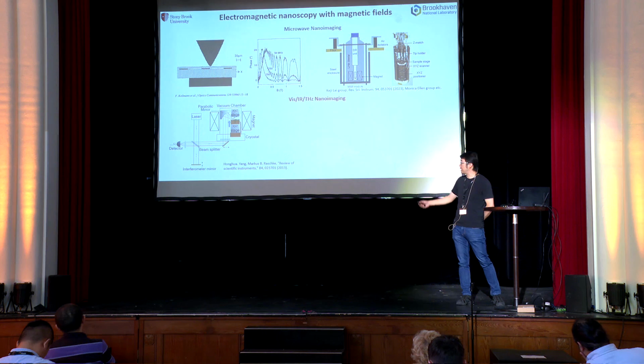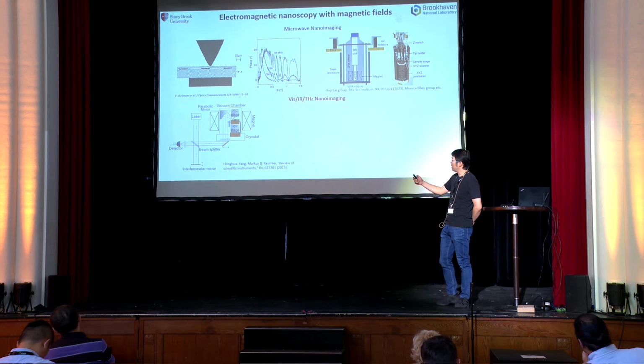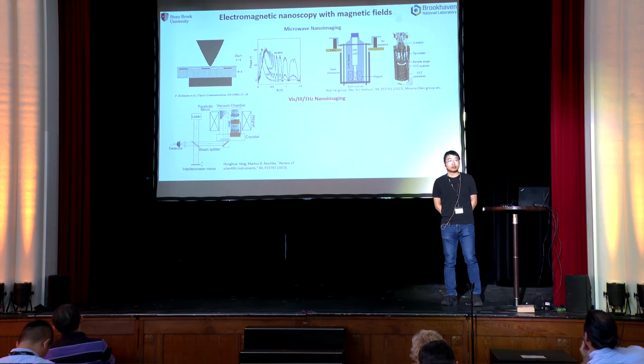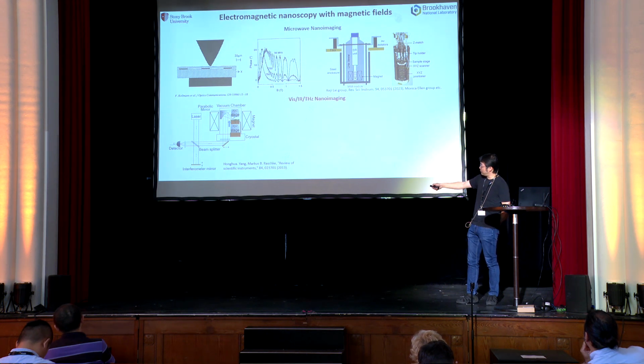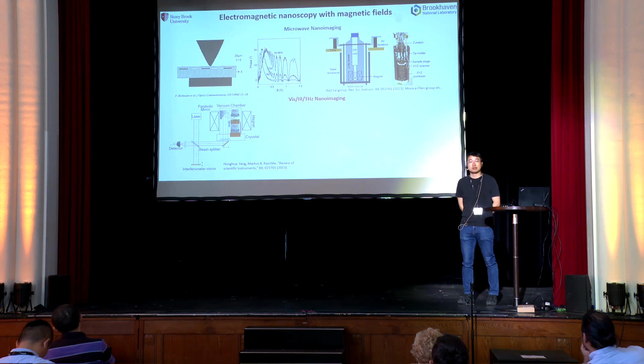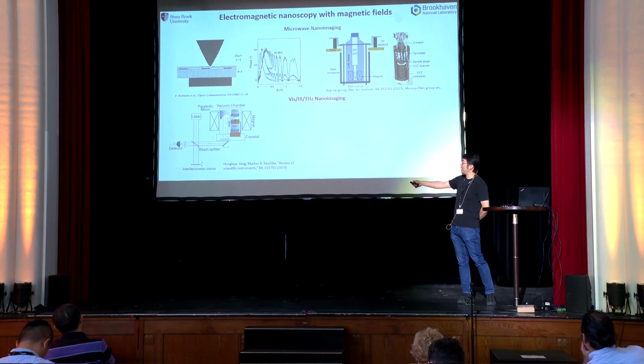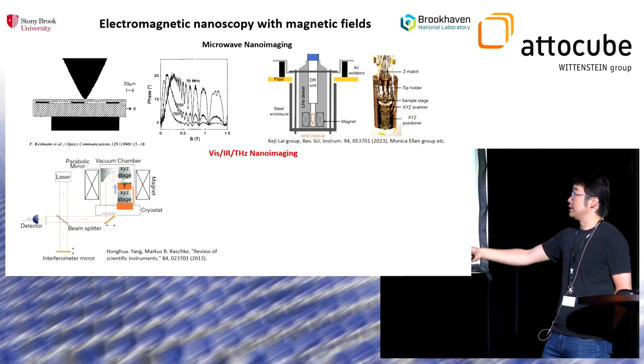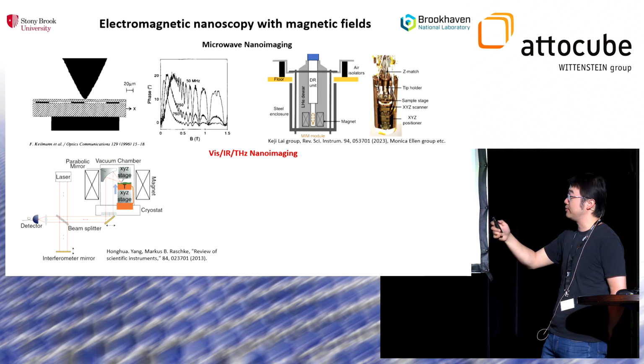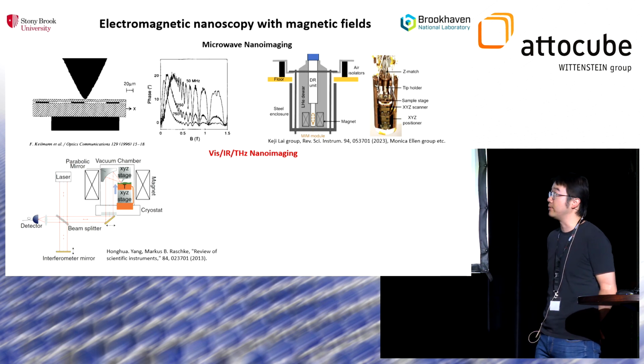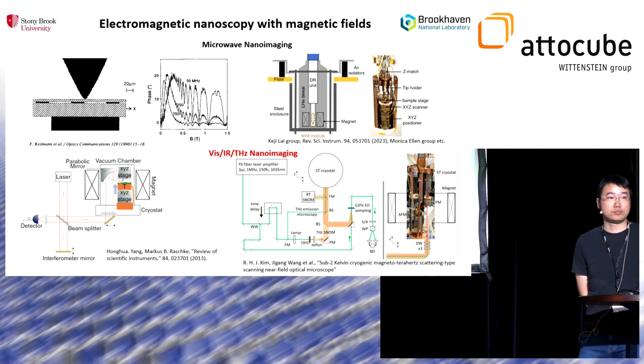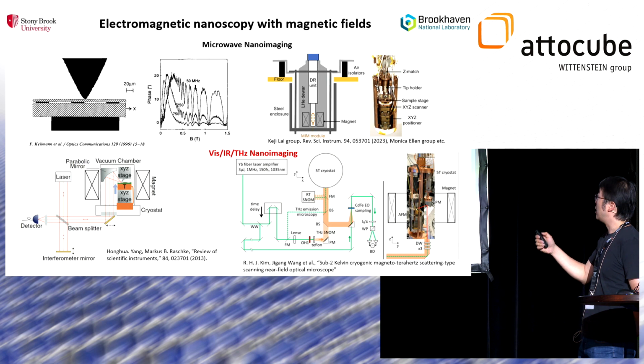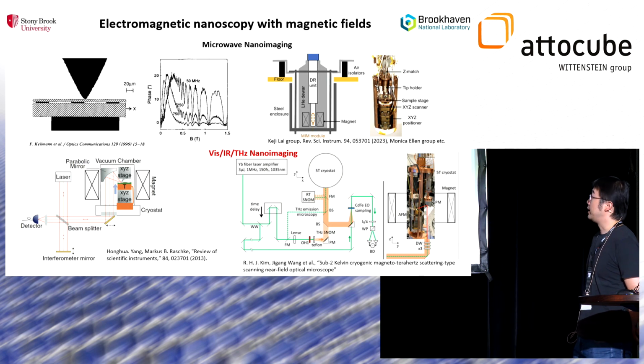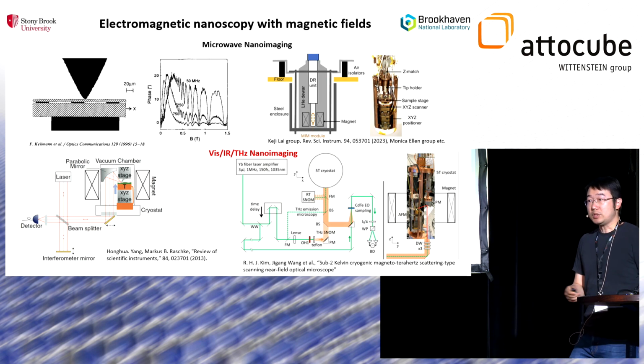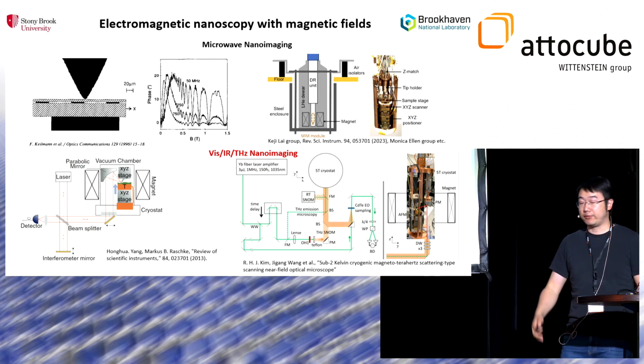Because, for example, proposed by Markus many years ago, he demonstrated that you can do this at a cryogenic temperature, but with a very bulky optical detection system, and you have to put a parabolic mirror inside of the chamber so that you can focus light and gather scattered light, which needs a very high NA objective, right? Of course, I said bulky, not only for his system, but all such systems are kind of bulky compared to other AFM type of system. So this is another example from Jigang Wang's group at Iowa State University. They managed to do this also with 5 Tesla magnetic field and with terahertz SNOM, right? He also used a wet system, that is, you have to use liquid helium.